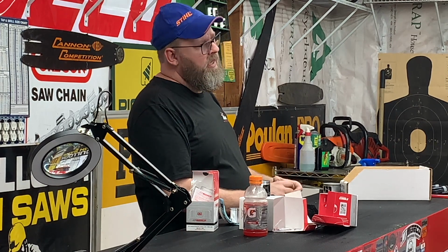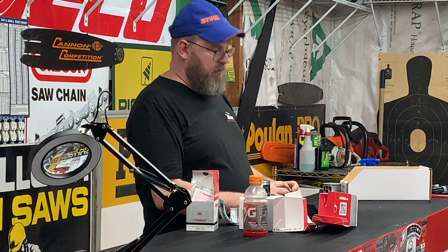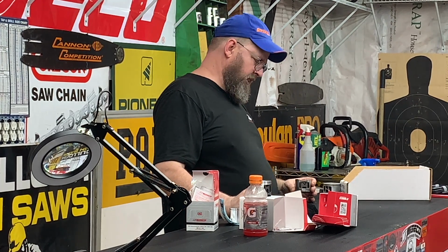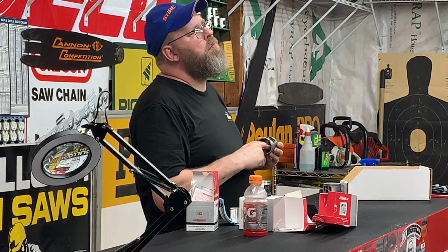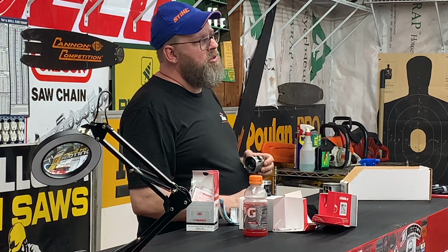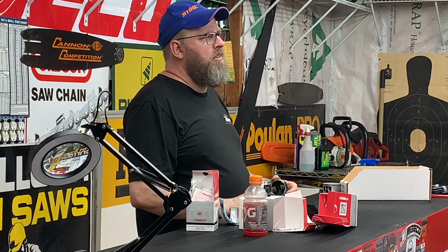In addition to the ring turning all the way around, which your customer will tell you, oh, the piston must have been defective. It was defective from the start, you would have hung a ring right away. Destroyed your top end. In fact, that has happened a couple times. Then, when we send the piston back for testing, the Rockwell hardness has been cut more than in half. The piston has been so hot under the dome that the alloy has turned blue, kind of a gunmetal blue. If you saw that on a crank, you'd think that's part of the normal hardening process. Or if you strip the paint off of a bar, looked at the edges of a good quality bar, you'd probably see some bluing. That's a no-no on a piston.